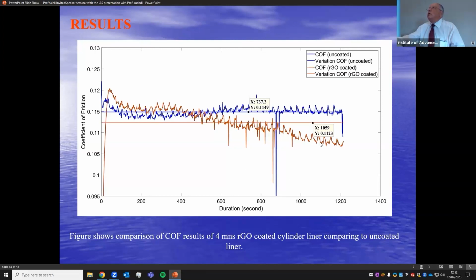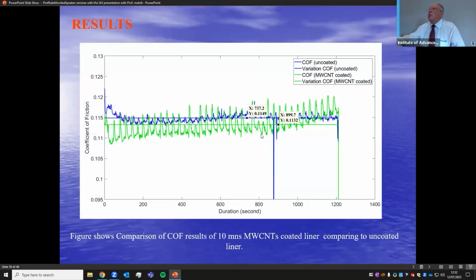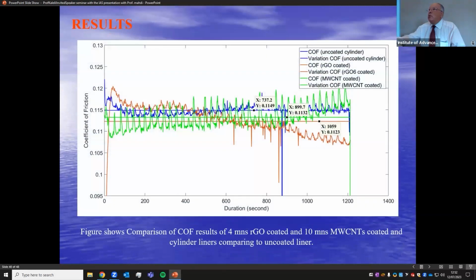You see here the red one is RGO and the other one is uncoated. And here you see the MWCNT coated also, and MWCNT was less than the uncoated one. But the MWCNT coating was 9-10 minutes. It was not 3 or 4 minutes. You cannot succeed in that. So this is uncoated, MWCNT coated, and RGO coated.